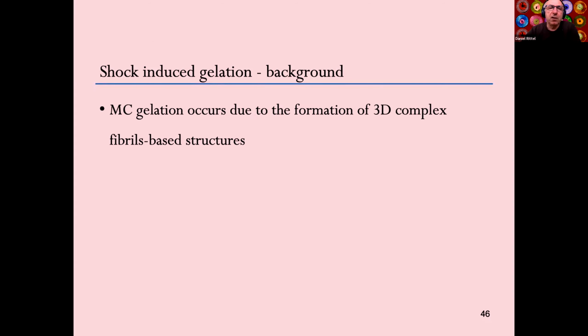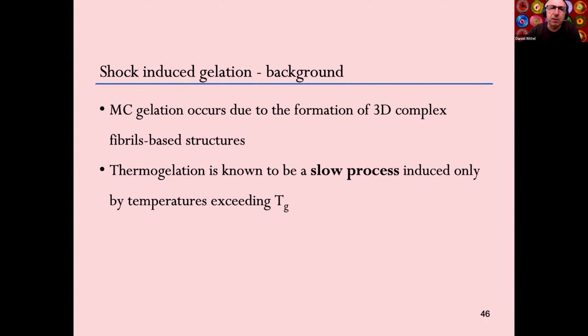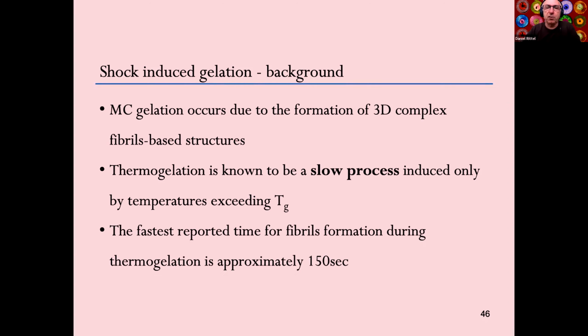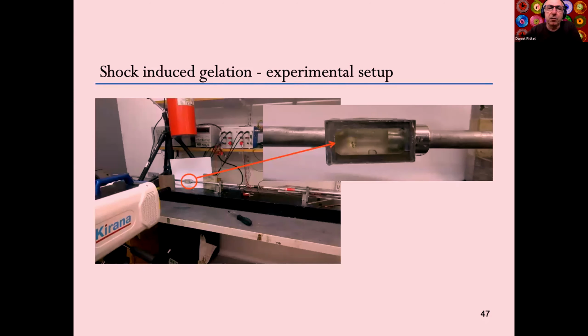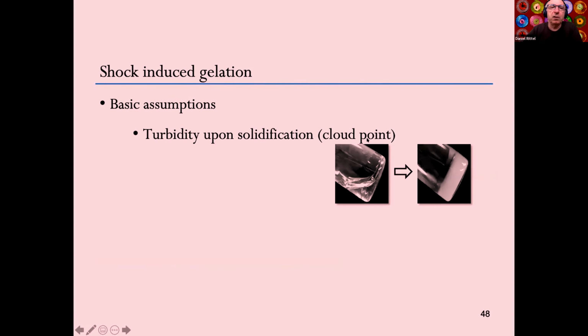Well, shock-induced gelation, that's what I want to talk about. Gelation is usually the realm of temperature. You increase the temperature, you have a slow process, and your gel solidifies, but in a few minutes for a typical sample size. So what do we do now? We use a high-speed Kirana camera. We have a chamber, we have one Hopkinson bar, it's full of gel, and we shoot. As usual, we look for turbidity that will indicate some phase change.